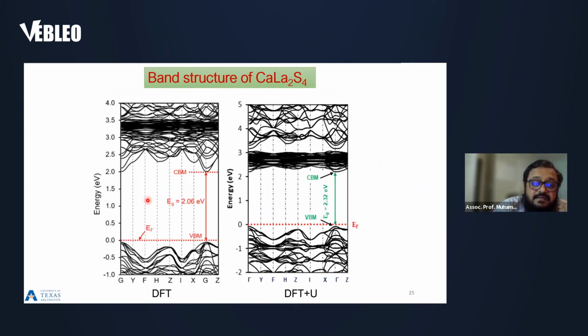A DFT-only band structure shows a band gap of 2.06 electron volt, where the unoccupied 4f electron shows just above 3 electron volt. And this mix is basically those lanthanum 5d orbitals and some of the sulfur p orbitals. Now we add a U value on the lanthanum 5d orbital.